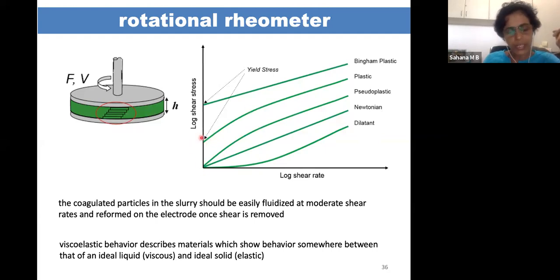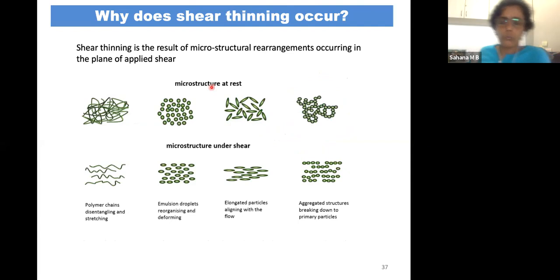We need a particular amount of shear for it to flow, and that is called the yield stress. Until the yield stress is reached, for example, carbon black is agglomerated together in a solution of PVDF NMP mixture, so we need some force for it to slide. That is the yield stress. In the plastic one, the response is not linear even after the yield stress, whereas in this one, it is linear after the yield stress. Why does shear thinning occur? Shear thinning is after the yield stress. What happens is, as we increase the shear, just give me 1 minute.